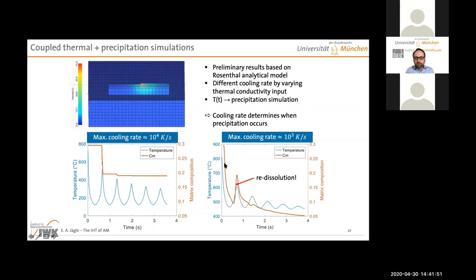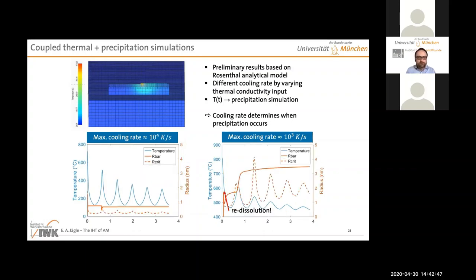And here you have a completely different behavior. You have a lot of precipitation happening. At the end of these 1, 2, 3, 4, 5, 6 reheating peaks, you have basically everything precipitated out of the matrix. And you see that already the majority of this precipitation happens not during reheating actually, but during the cool down from the initial deposition. And that matches precisely with what we observed in the experiment, right? Where the cooling rate is the driving factor and you have way more precipitation at the very top. It's not the reheating that is very relevant. It's really the cool down from the deposition. And if that cool down is slow, which is the fact at the top of our single thin wall, then you have a lot of precipitation. So even though this is not yet ready for prime time, the model already tells us qualitatively exactly what we're seeing in the experiment. Okay, this is basically the same thing, but with radii instead of precipitated.